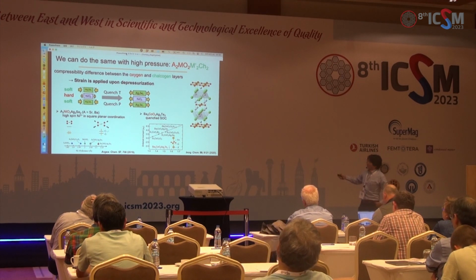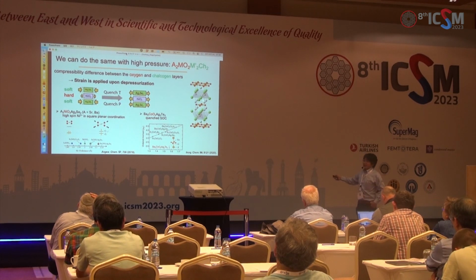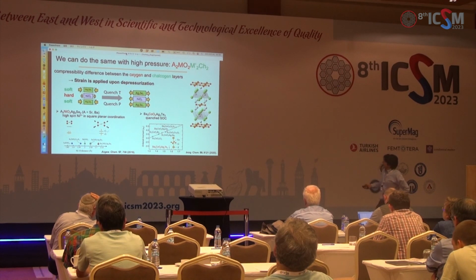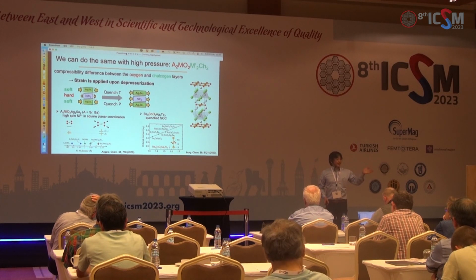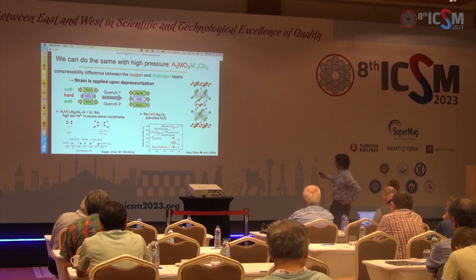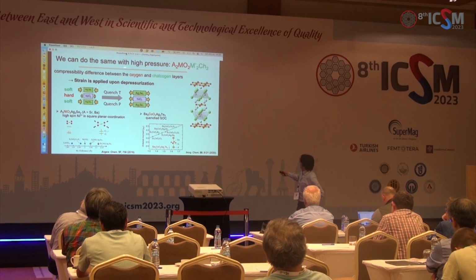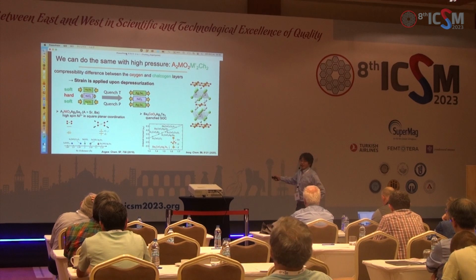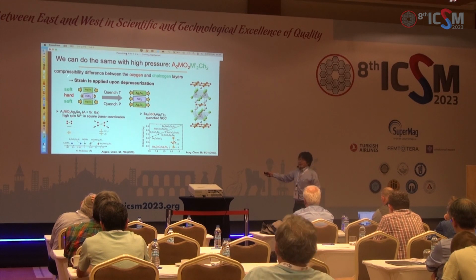Maybe you know hard-soft acid-base theory. So actually, this is a hard layer and this is a soft layer, alternating with each other. But when you apply pressure, the soft layer becomes much smaller than the oxide layer. Then what happens is that we stabilize these materials by applying pressure. Ambient pressure synthesis is impossible, but somehow at a pressure of 5 GPa or 10 GPa, we can get these materials. So this is the crystal structure at 5 GPa.